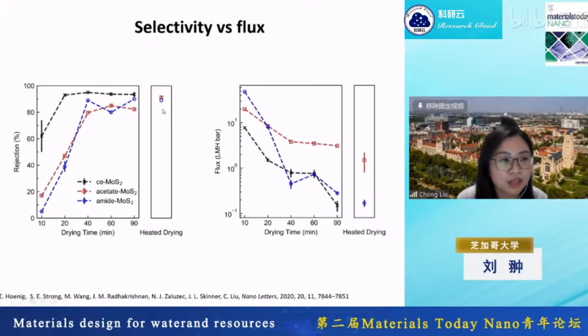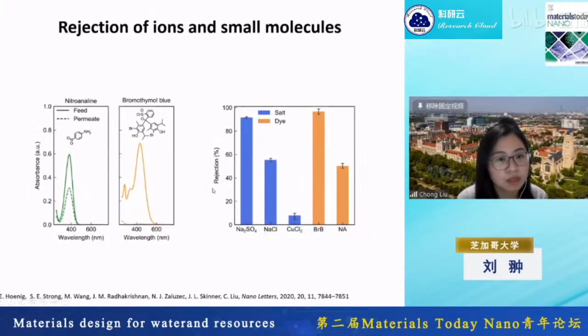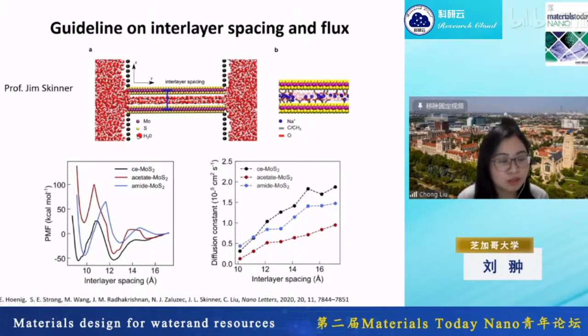And at the end, we can totally dry the membrane and rehydrate the membrane, and you have the highest rejection and flux at the same time. And we also showed a clear size cutoff of a big molecule dye. Then the critical thing for us in this work is we want to understand the way the molecular spacer is playing here, like how you choose this molecular spacer.